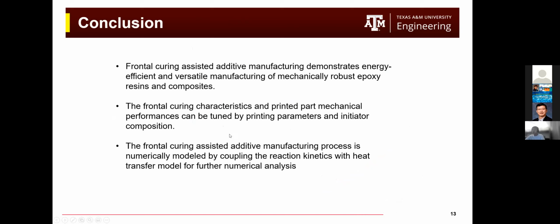So here I will conclude. At first, the frontal curing assisted additive manufacturing demonstrates energy efficient and versatile manufacturing of this epoxy composite, and it shows good mechanical properties. The frontal curing characteristics and the printed part can be tuned by the printing parameters and the composition of the epoxy inks. And then we were able to numerically model the additive manufacturing process by coupling the reaction kinetics and the heat transfer model. And this is good for future numerical analysis.